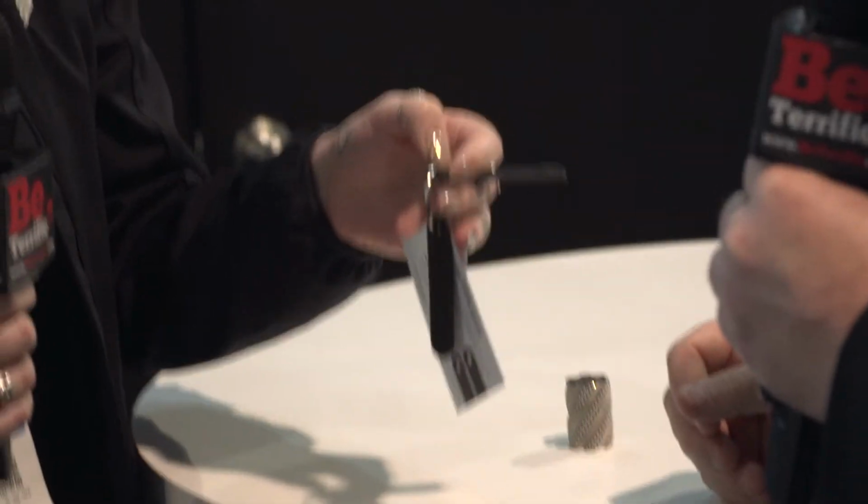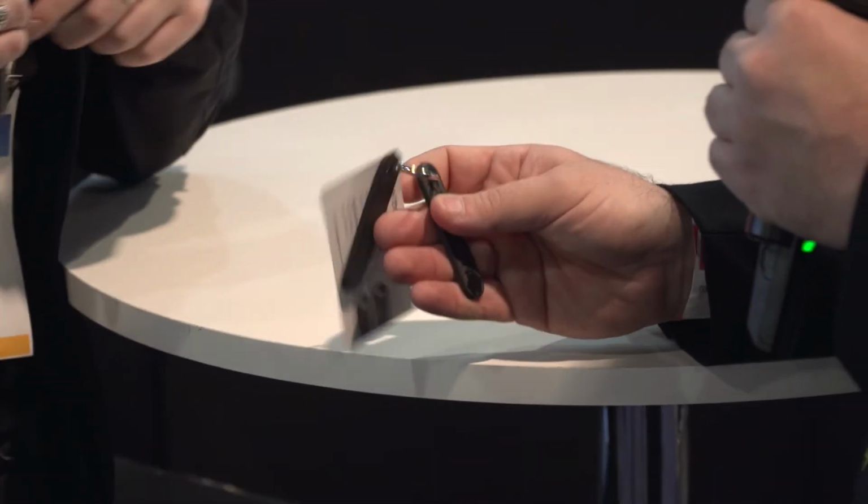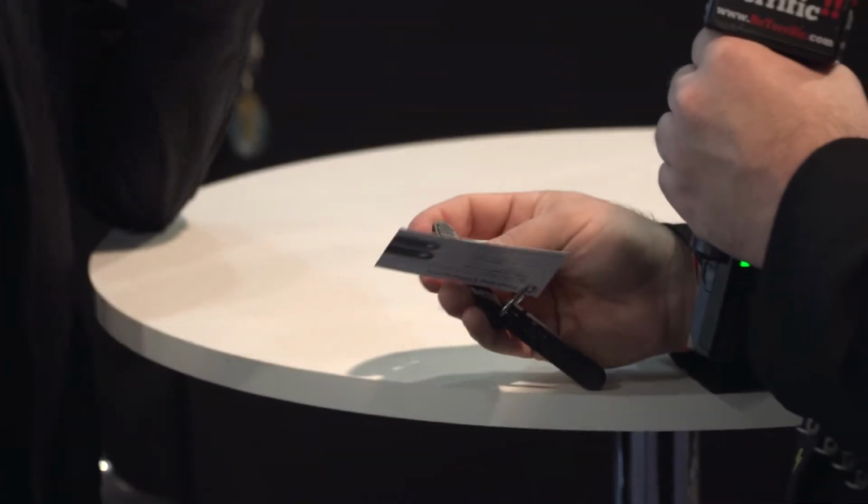Because they look the same from the outside. So we cut them out. It's hard to see up close right now, but on the inside, you can see there's a difference. Here it's cut out, so it's just our chopped carbon fiber. Here there is a layer inside, so we lay down continuous strands of carbon fiber onto the inside, and we have our own slicing software. You bring a regular STL file, and we will help you optimize where to put those reinforcement fibers and what direction you want, in order to really add strength to it. Usually you don't reinforce the entire part. It's not usually worth it. If you can selectively do it, though, you add strength or different properties, depending on what you're looking for, into your part.